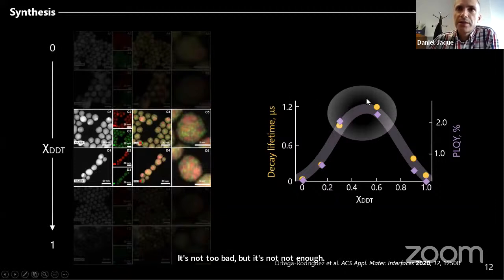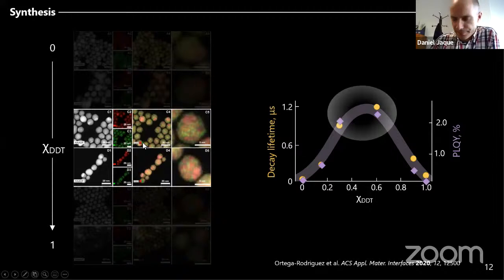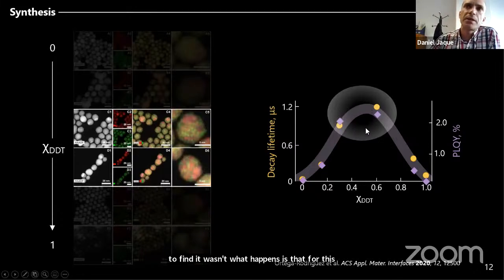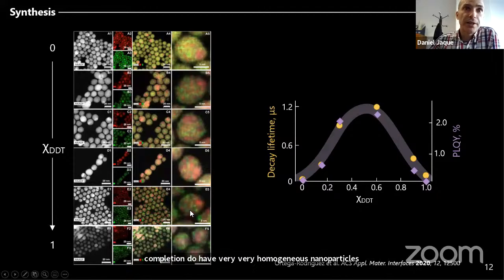But why is this happening? Why do we have this maximum in the quantum efficiency or in the brightness? If you look in detail at the TEM pictures and the compositional picture, where red is silver and green is sulfur, what happens is that for this particular synthesis condition you have very, very homogeneous nanoparticles. If you compare here, they are less homogeneous than here.